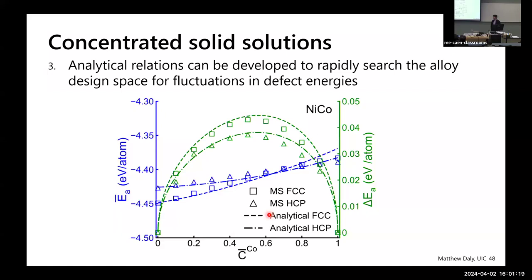Sheldon, part two. So you showed glass grain, not a crystal grain. It's a complex problem. The problem is functionally grading it, right? That is not amenable to electrodeposition. Because what electrodeposition is good at making is sharp boundaries, because you are turning on your power supply and then turning it off, or flipping it on and off really quickly. If you try to gradually change the waveform, what you'll do is you'll just grow one really long crystal.